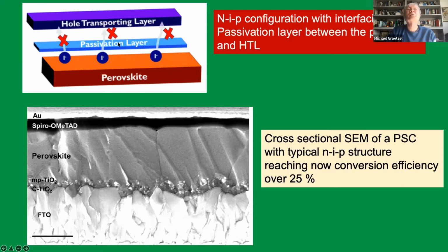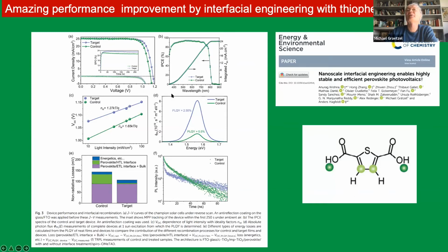And so what do you choose? Well, your chemical intuition has to give you the inspiration there. You have an infinite number of choices, and chemistry knows no limit. But I'll just give you two examples now. One is this thiophene molecule. It's a good passivator. The sulfur will bind with coordinatively unsaturated lead on the surface, and the carboxylates also hydrogen bond with some of the A cations. So this turned out to be a very good passivator.